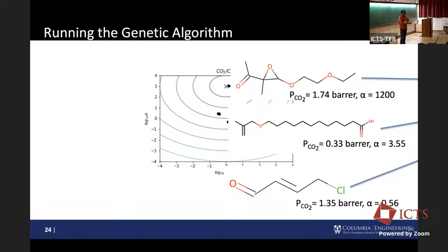Apparently, so I mean, polymer chain length really should matter, right? And its morphology should really matter. We put in morphologies, crystallinity going from 0 to 80%. It doesn't seem to affect the permeability. So it tells you the data is lousy enough that it's really not sensitive. So we'd need higher quality data, which distinguishes on that variable, if you want to go look for it. There could be an application.